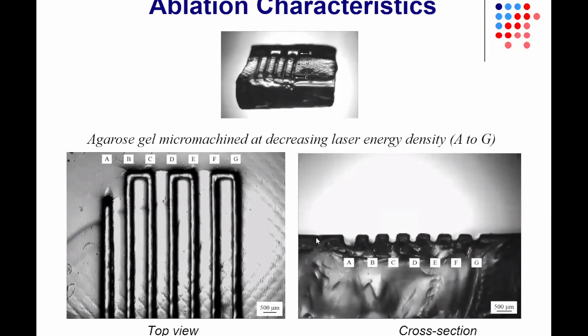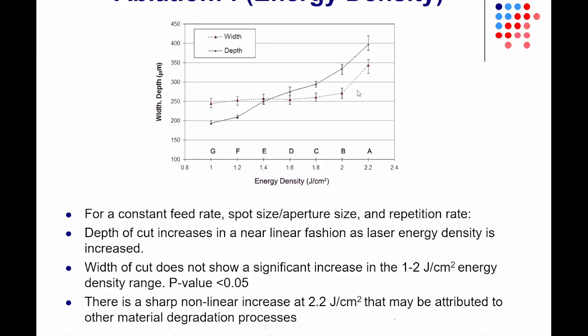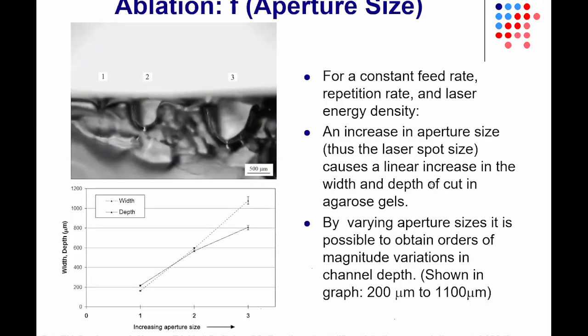Here you can see some examples of the channels, with different channel widths created through changes to the laser energy density. As you change the laser energy density, you have significant changes in the width and depth of the channel. You can see here that it generally doesn't show a significant increase in the width of the cut at 1 to 2 joules per centimeter squared, but then there's a non-linear increase at 2.2 joules per centimeter squared that may be due to other types of material degradation processes. You can see here, again, an example where you change the aperture size. By changing the aperture size, you can change the dimensions of the channel.